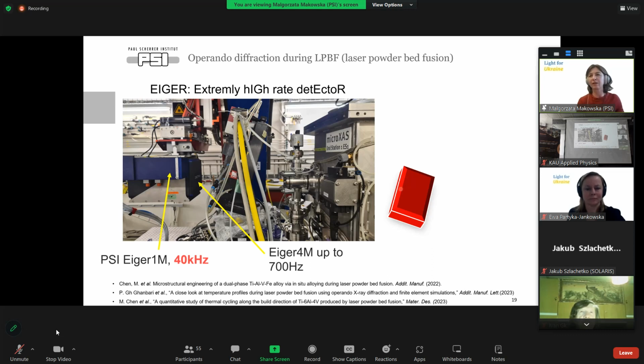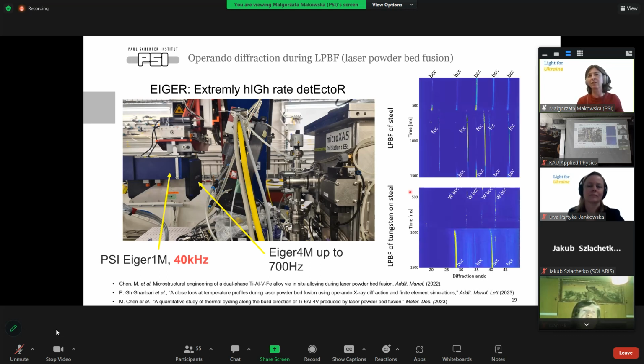And here comes the X-ray beam. So we are sitting somewhere here. Here is the diffraction detector. And we scan with a laser. And during scanning with the laser, we can track the diffraction pattern with a very high speed, currently up to 40 kilohertz. And we can see how during solidification we have transformation of different phases in steel.